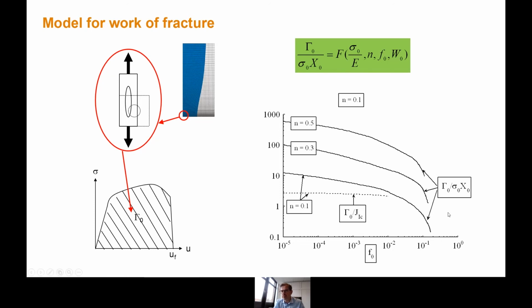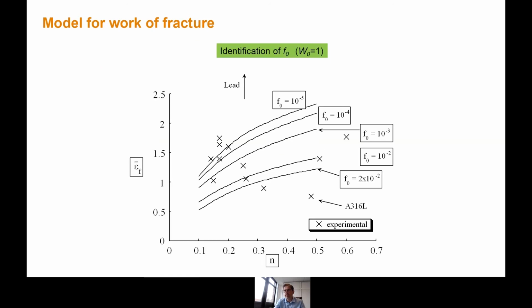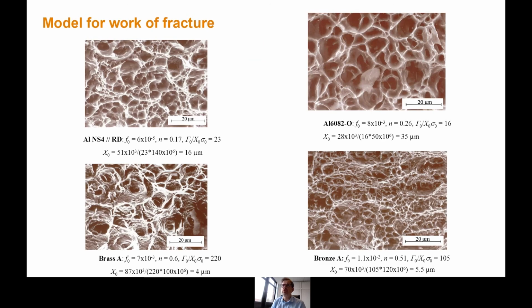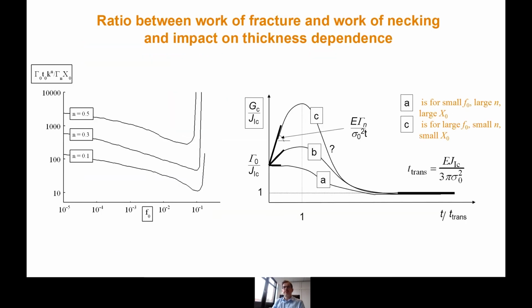And on top of gamma zero, you also have the work of necking. In order to calibrate the model, I had to see if we could get a good prediction of the fracture strain. So to fine tune the F0, I will skip these details. We also measured on the fracture surface the void spacing by measuring distances between voids. So I will skip that.